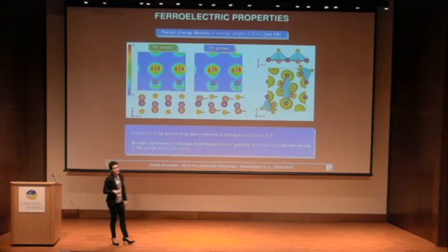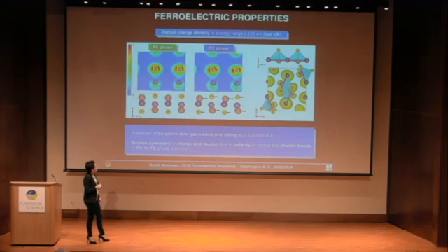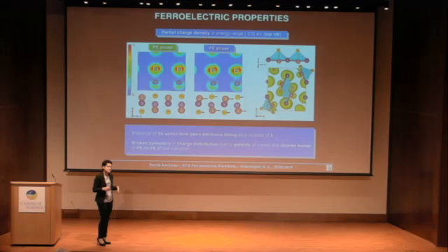Moreover, this model is confirmed by the presence, at the top of the valence band, of an active lone pair at the antimony site. It is important to notice that this is the same for both the paraelectric and the ferroelectric states, because the presence of this active lone pair is due to the strong asymmetry of the antimony site, and that is related to the bipyramidal arrangement of the chains.